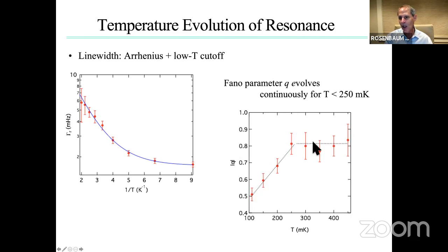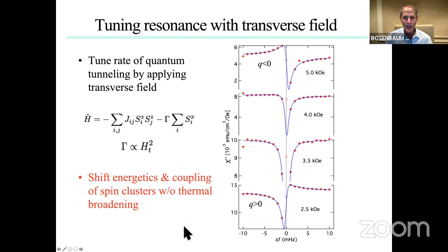So I'm getting close to one of the limits where it's really the interactions between the clusters themselves that are dominating, and there's not much quantum interference left. Okay, so this tells you something about the system and the energy scales in the system. It's not terribly useful otherwise. However, remember, we have a transverse field, and you can also tune this resonance by applying a transverse field. Let me remind you of the Hamiltonian here, where this gamma, I'm sorry, the gamma here is the transverse field, not the line width in the Fano resonance. I apologize, I should have changed that.